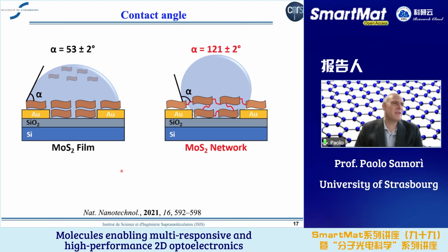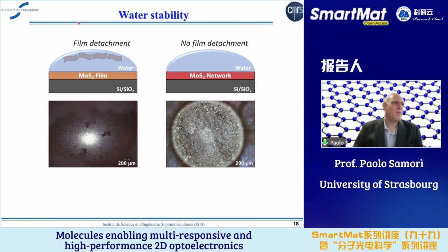We also have been studying by contact angle, and we observed that the film was hydrophilic and the network became extremely hydrophobic. And actually, this hydrophobicity is such that when we expose the films to water, in the case of the film, after a few minutes, there was a detachment of the film from the silicon dioxide, whereas the network was extremely stable. And this is very interesting for water-based applications.